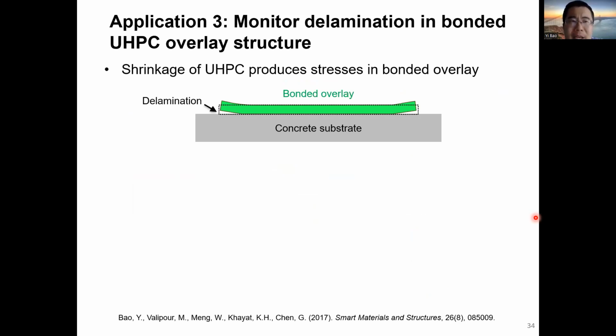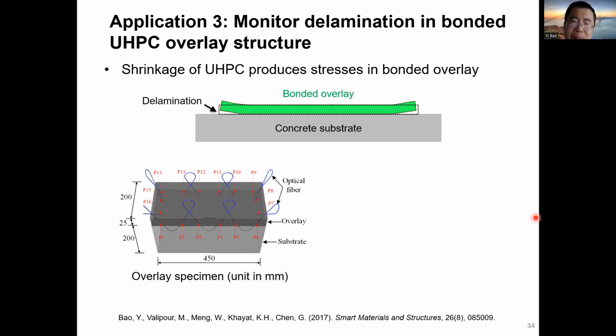And then we extended the application to monitor interfacial delamination. This is another challenge for the layered structures, such as the bridge deck overlay or a pavement overlay. So UHPC has been used as the overlay material because of the high mechanical strength and durability. However, in real projects, engineers have identified early age delamination at the interface between the overlay and the substrates. And this overlay delamination was related to early age shrinkage and the change of relative humidity. But there was a lack of effective methods to monitor the interfacial delamination.